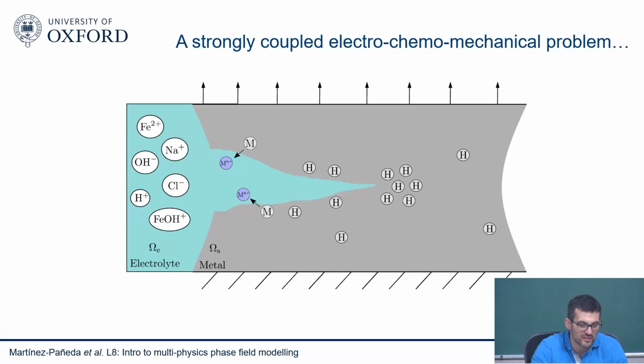Imagine this is a sketch showing a typical scenario of stress corrosion cracking. A lot of things are happening. You have some sort of electrolyte, it could be seawater. You have your metal, which is being subjected to some mechanical deformation, so there's mechanics in there. In the electrolyte, you have many ionic species that are diffusing through your electrolyte, similar to the hydrogen uptake problem that I was discussing in the seminar. Those species are moving around due to fluid flow, due to electromigration, due to diffusion.